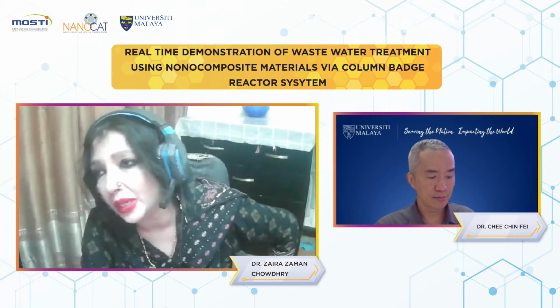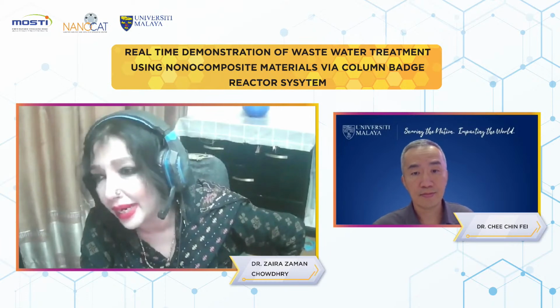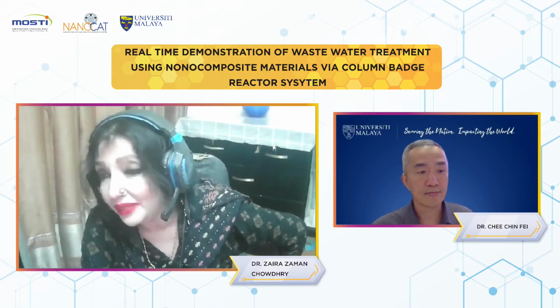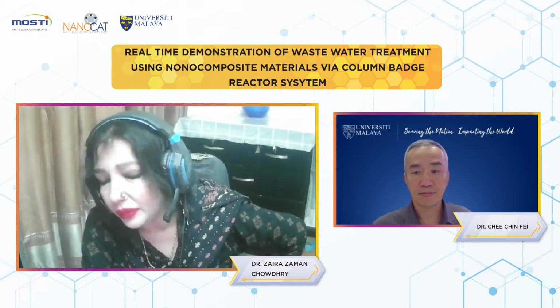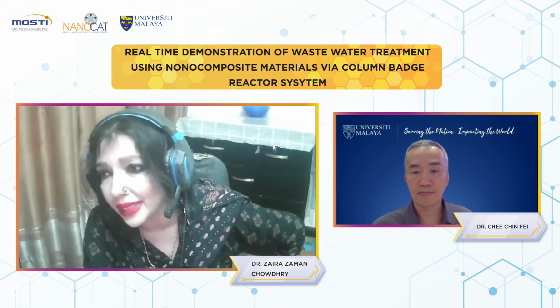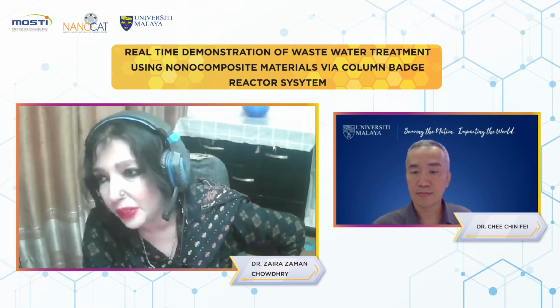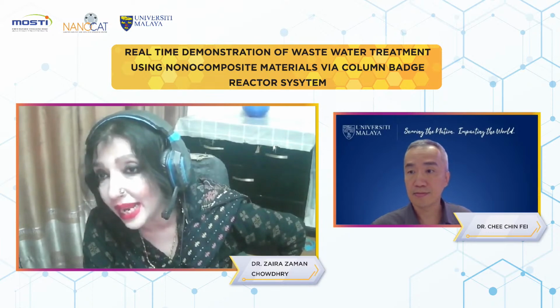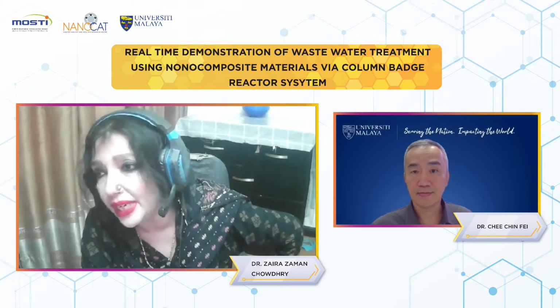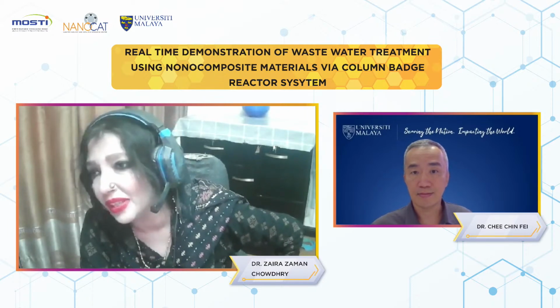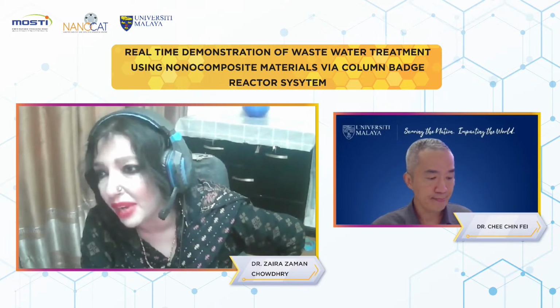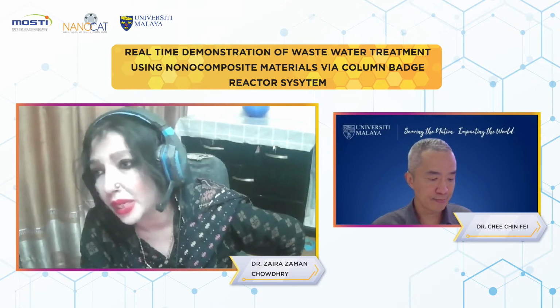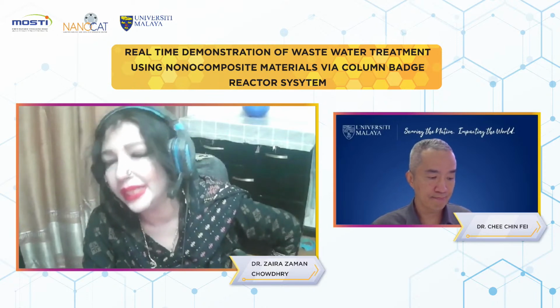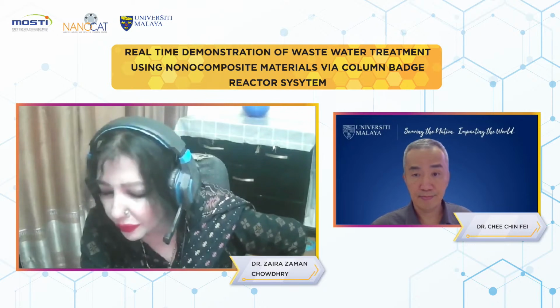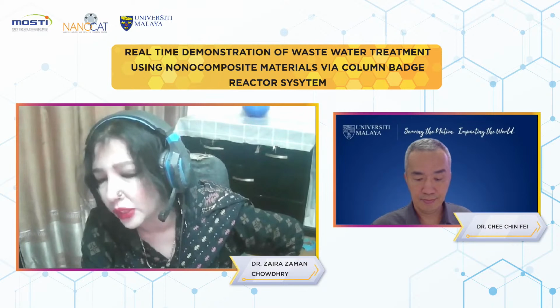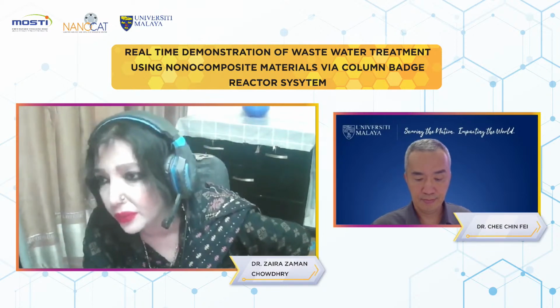This is a special kind of reaction, the water-gas shift reaction, where potassium or sodium, any type of metal, will go for an intercalation reaction. Because activated carbon has graphite-like layers, right? So this potassium will run so fast inside the pyrolysis apparatus, it will extend the distance between two or three graphite layers. So the internal surface area, which we call the basal plane of carbon, will be increased, and ultimately our surface area will be increased. This is a special kind of reaction in the presence of alkali metal oxide, metal hydroxide. We call it the water-gas shift reaction. Then we use carbon dioxide gas. It is an activating gas in that case. And nitrogen and argon we always have to use before any reaction starts in the pyrolysis apparatus to evacuate oxygen, otherwise ash will form. We want to reduce this ash in the carbon.